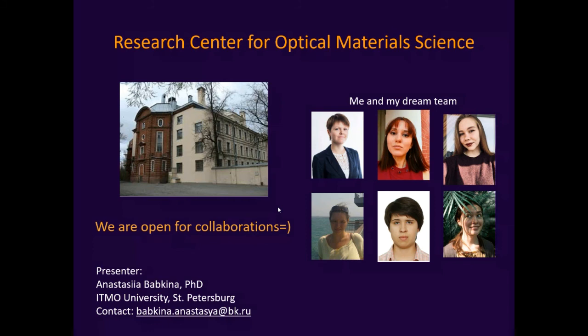Okay. Thank you. And the second question from Andreas: have you done luminescence lifetime measurements to better understand the quantum yield? Yes, thank you for the second question. Yes, we have made luminescence lifetime experiments. The results were very tricky, and that's why I haven't shown them here, because for almost every glass sample with different crystals, the average lifetime was about 10 nanoseconds. This is okay for these crystals, but it did not follow the heat treatment duration or temperature, and it was very peculiar. So we are working on it now.